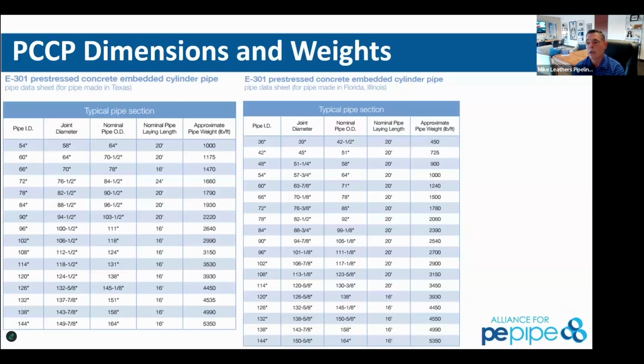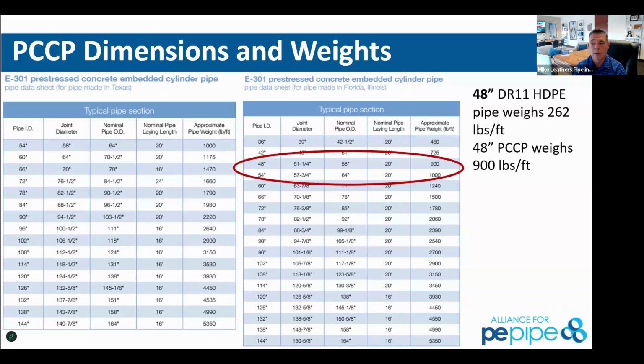As an example of this weight, comparisons for similar sizes as a potential rule of thumb or a quick calculation, PCCP can be about 3 times as heavy as HDPE. So you're handling 1,000 pounds per foot versus 300 pounds per foot in this example, where the concrete, mortar, and joints are all remaining as the manufacturer made them, which is critical. So if the contractor's equipment bangs a pipe unloading it or installing against another pipe or the truck or the ground or an excavator or the trench box, and that contractor knocks off some concrete or damages the joints or delaminates the interior or exterior coatings, the question is, will they fix it? And that's often where you can have long-term problems, or will the inspector even catch it?